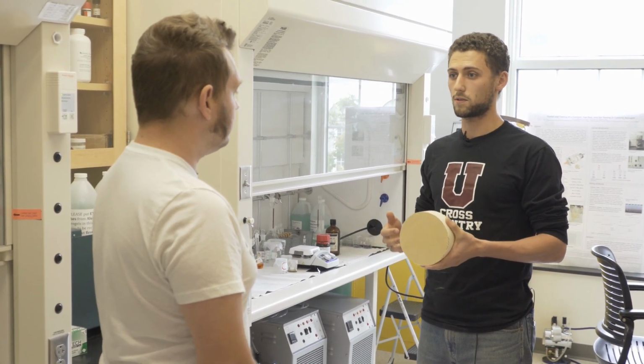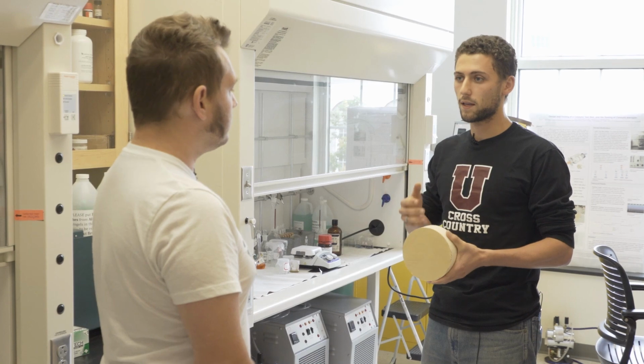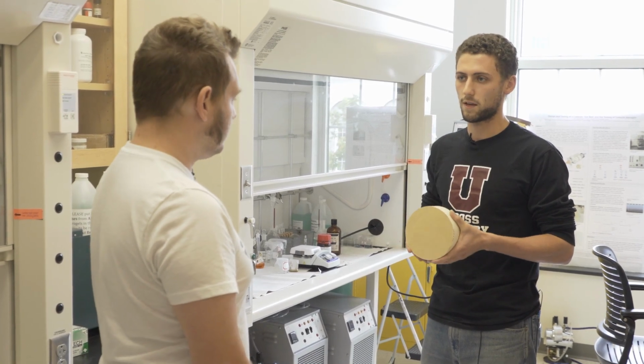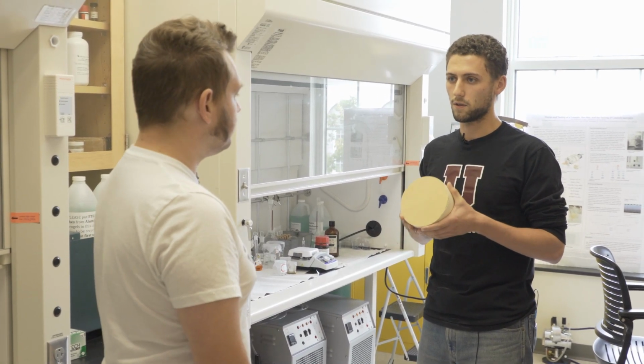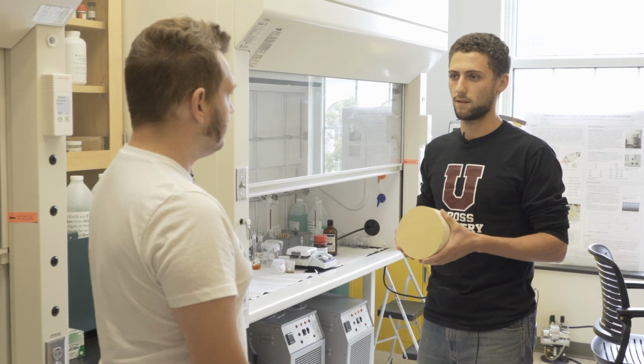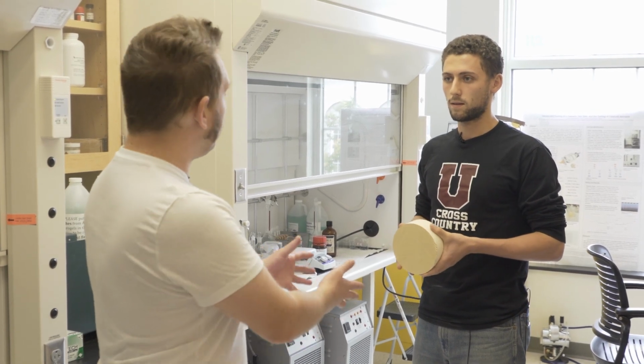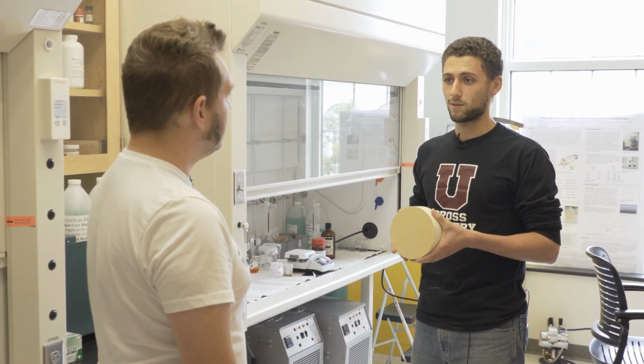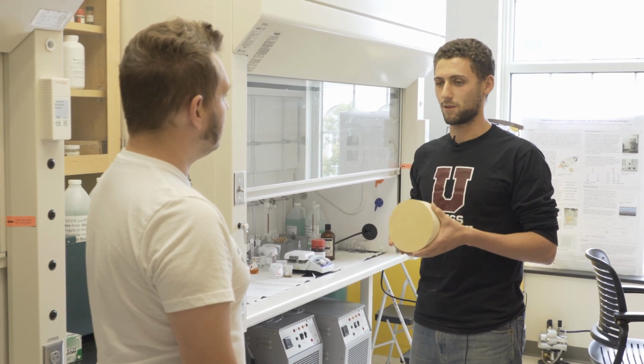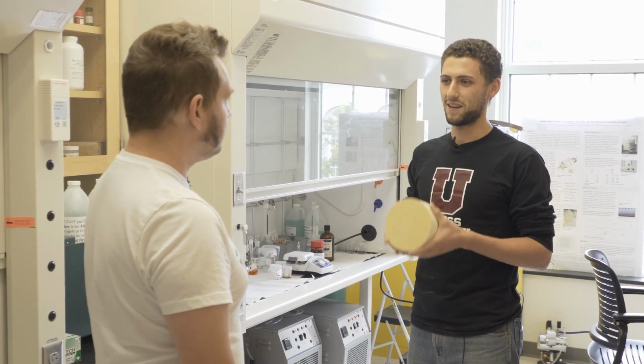So what we wanted to do is see how much aerogel can we put in those pores as well as on the surface that you see. Cool. And then we can hopefully use that to increase the catalytic activity that we're getting. So what did you find in your research? We found something that's actually really promising, though it seemed a little bit disappointing at first.